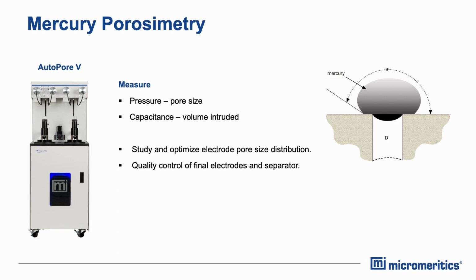Because mercury is a non-wetting liquid, the contact angle to the surface is larger than 90 degrees, and it does not intrude into the pores voluntarily. By measuring the change in capacitance, this method determines the volume of intruded mercury and can then relate it to the pore sizes. This method is in general very well suited to characterize the porosity of finished electrodes, especially if they include macropores that cannot be detected by gas adsorption.